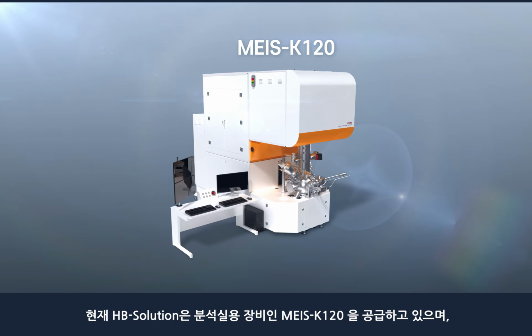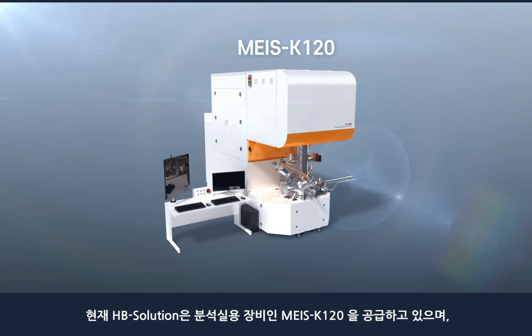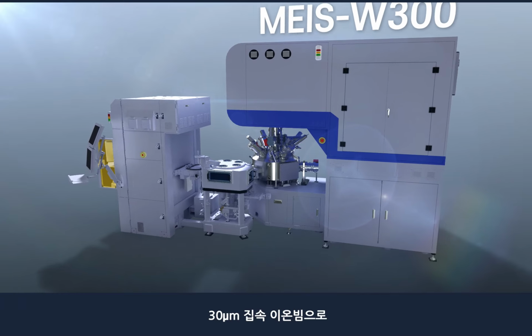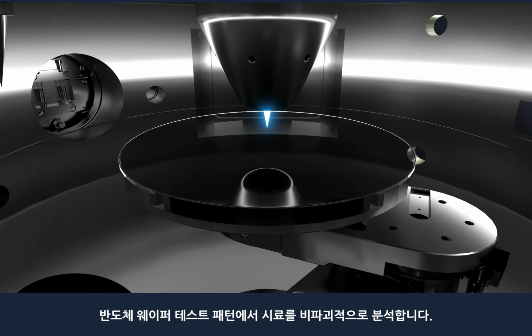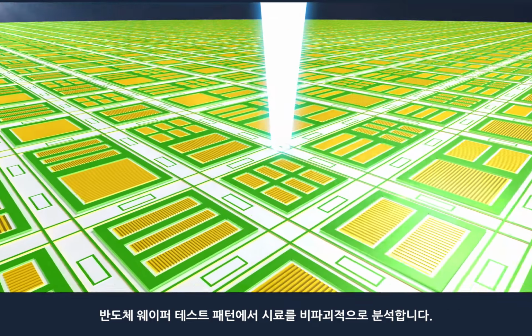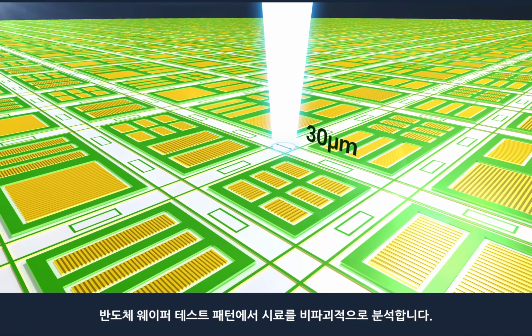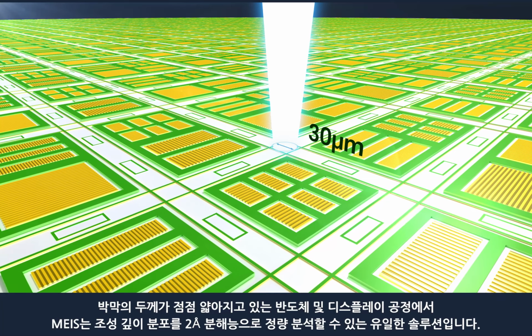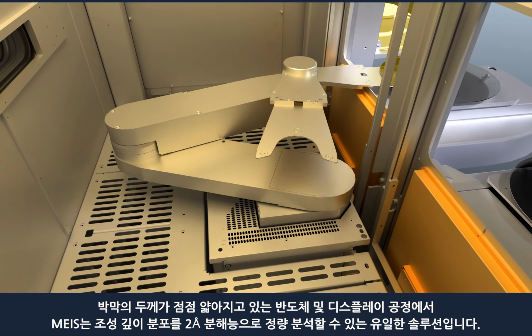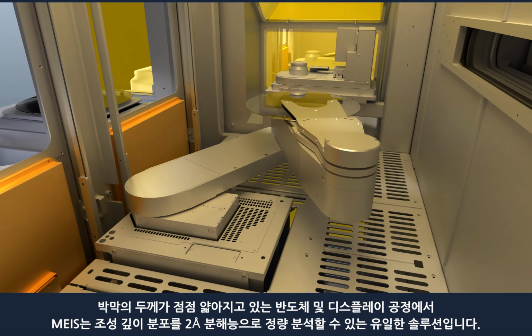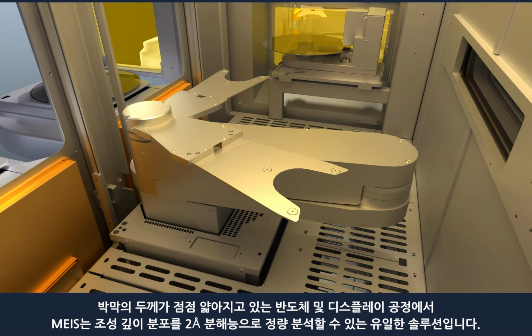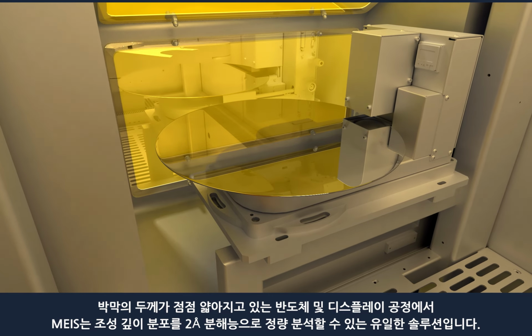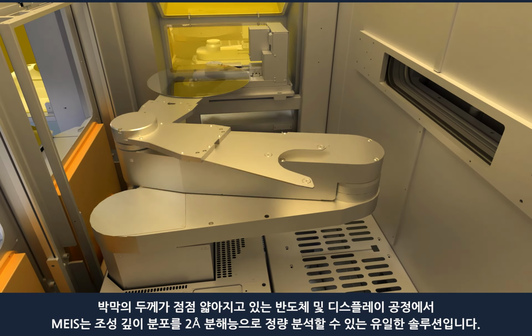Currently, HB-Solution supplies MEIS K120, a system for laboratory, and has developed TOF-MEIS for measuring a 300 mm wafer. TOF-MEIS for a wafer measurement uses a 30 micrometer focused ion beam to analyze samples in a semiconductor wafer test pattern using a non-destructive method. In the process of manufacturing semiconductors and displays, where the thickness of the products decreases, MEIS is the only solution that can quantitatively analyze the compositional depth distribution with a 2 angstroms resolution.